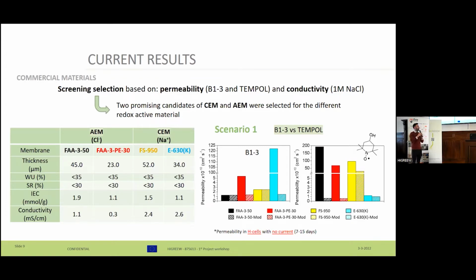According to the HIGREEW guidelines, in scenario 1, we were dealing with the B13 molecule and the TEMPOL molecule. And in these membranes, we were required to test how was the permeation of the active species in pristine membranes and its modified version. And as you can see in the graphs, in most of cases, the permeation when using our modification was successfully reduced. Such permeability tests were done in H diffusional cells with no current, but during 1 week of evaluation.